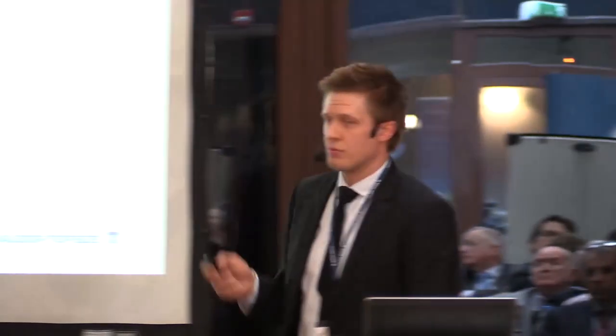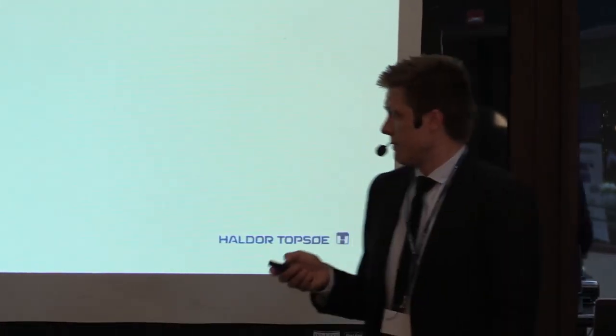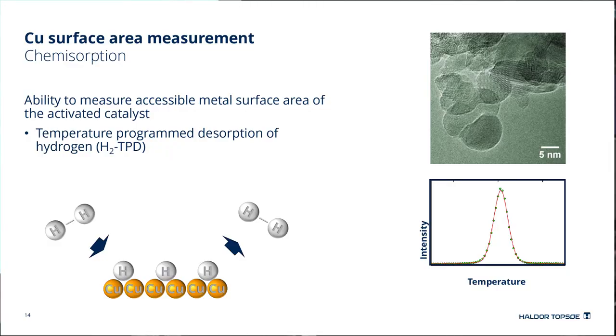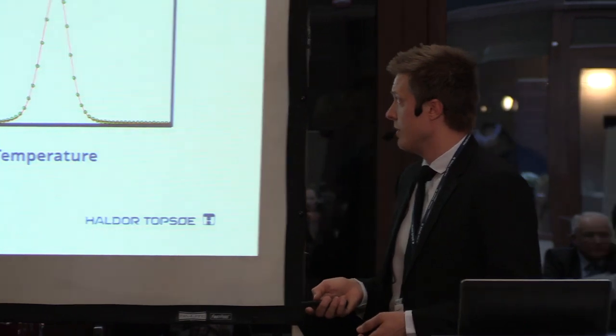And among the different tools we had available was the temperature programmed desorption of hydrogen. So here, you come along with a probe molecule, it's hydrogen. You can saturate your copper surface with the hydrogen, then you shift to another gas and you flush away all the residual hydrogen. Then you increase the temperature in a linear ramping and the hydrogen will recombine and desorb and you'll get a spectrum like this. The area under the curve will be proportional to your copper surface area.